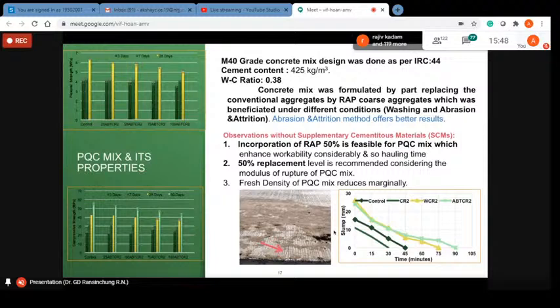As we know, in the mechanical properties of hardened concrete, we normally look at the compressive strength and the flexural strength, that is basically the modulus of rupture of the concrete. Right? In the case of compressive strength, no improvement was seen when the conventional aggregates were part replaced by the RAP materials. Whereas in the case of flexural strength, there was a reduction in the modulus of rupture when we incorporate the RAP materials by part replacing the natural aggregate. But a more appreciable flexural strength is achieved in comparison to compressive strength when the natural aggregate is partly replaced by the RAP materials.